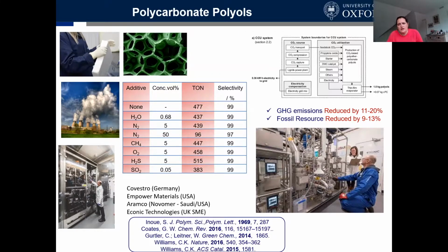In the center of the slide, you see some work that we did on using captured gas. I'm not going to run through all the impurities in the gas, but the short message is that we took some CO2 from a coal-fired power station. It went through purification before we used it. But when we did use it, we saw that the catalysis functions really well, even with the captured gas and with some of those impurities present.